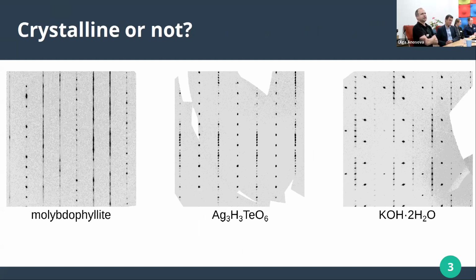My first crystal structure I had to solve was calcium telluride, and it produced one of these diffraction patterns, like you see them here, which defy the classical categorization of is it crystalline or is it not crystalline? Because when it's crystalline, you would think it's periodic, and when it's periodic, it should have a discrete diffraction pattern. Now you have these diffraction patterns with sharp, discrete spots and at the same time diffuse scattering. Sometimes you have diffusity to different degrees. And sometimes, like in the middle one here, you have spots that are not on a lattice, where you would suspect they're on a lattice.